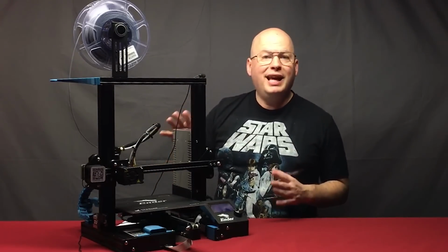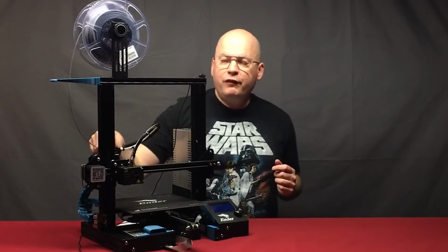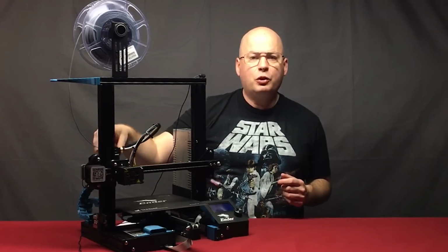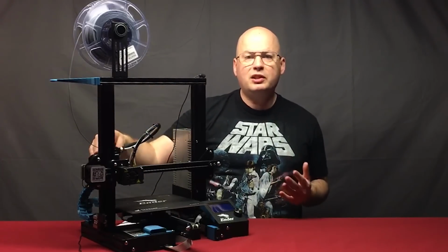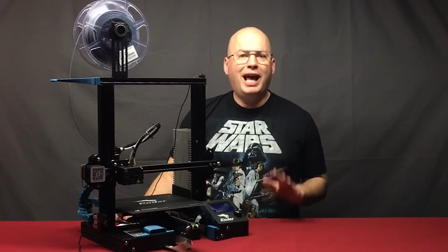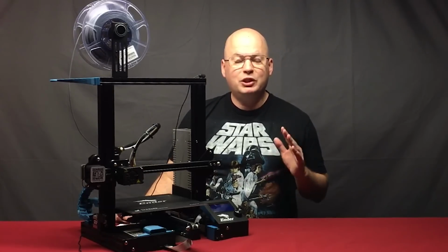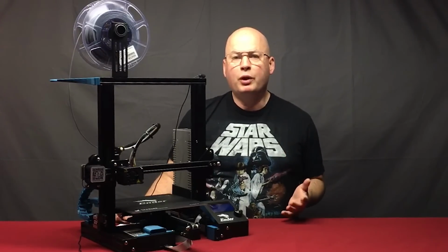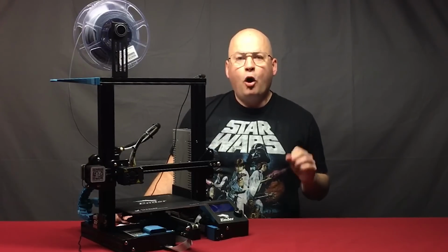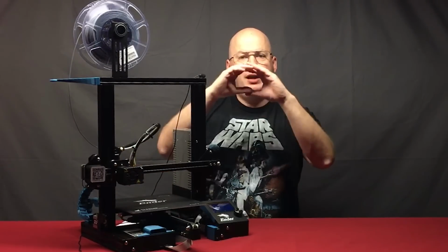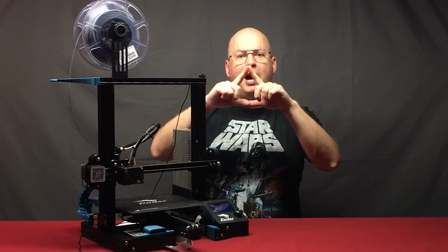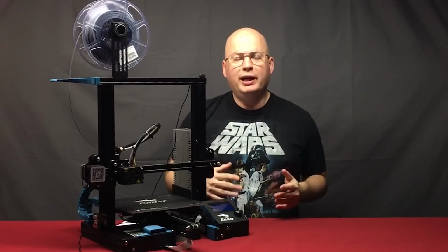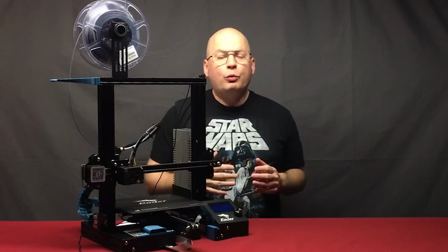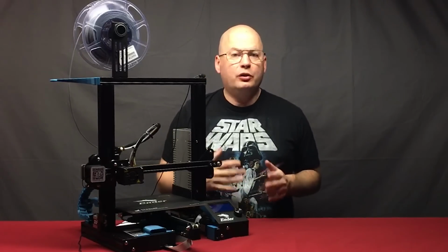Specifically on the Creality Ender 3, the filament guide on the extruder, where the little lever is that you squeeze on the spring, that is made of plastic. And in just a matter of weeks or even a month or two, the hole in that plastic can wear from being a hole to being more of a triangle shape from that filament rubbing through it, and it erodes down. It will start snagging and causing under extrusion on you.